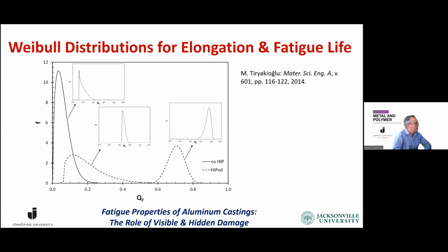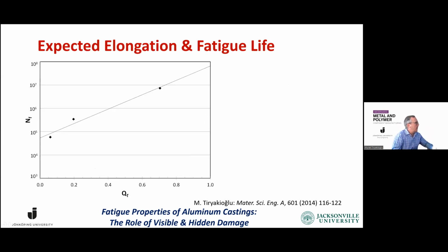Three Weibull distributions that we saw. These are from the Weibull distributions for the quality index versus Weibull distributions of the fatigue life that we saw. So when I plotted the average quality index versus average fatigue life, I saw a trend that clearly linked the effect of the quality index, or the reduced damage, to fatigue life.